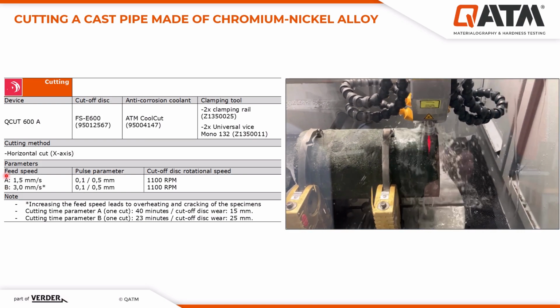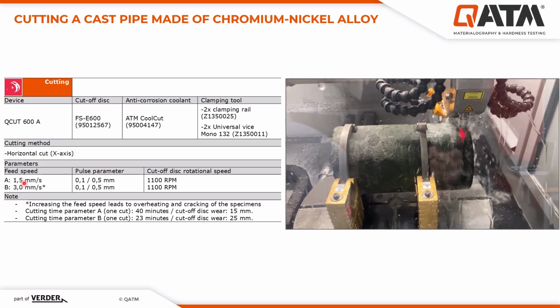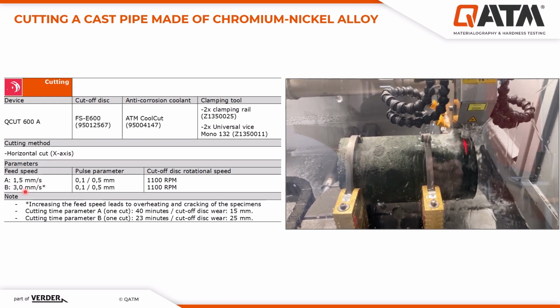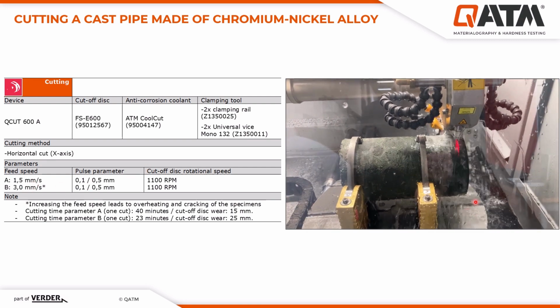The feeding speed can be from 1.5 millimeters to 3 millimeters, and the pulsing parameter is 0.1 forward and 0.5 millimeter backward, and the rotational speed of the cutoff wheel is 1100. By increasing the feed speed, we can overheat the sample, and sometimes there are cracks on the sample. And also, when you have a very large feeding speed, the wear of the cutoff wheel is also more. As you can see, with 1.5 millimeters, the cutting time is 40 minutes, but the wear of the cutoff wheel is 15 millimeters, and you don't have any overheat.